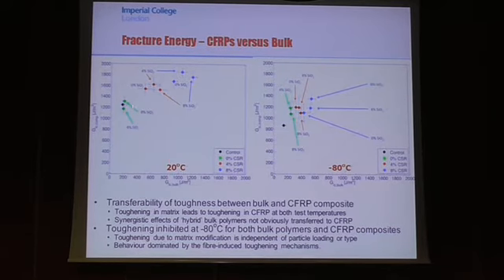We see that the black point here is our control, and when we add the silica, we don't really see any transferability of toughness. But when we add the rubber, the toughness of the composite goes up. There's not really a huge change in toughness when we add silica.